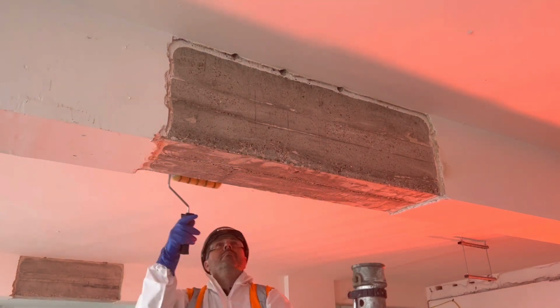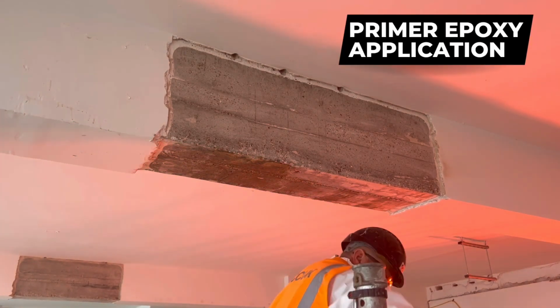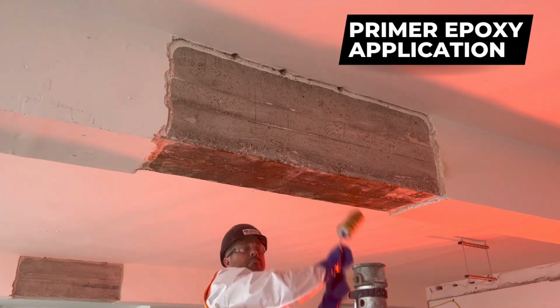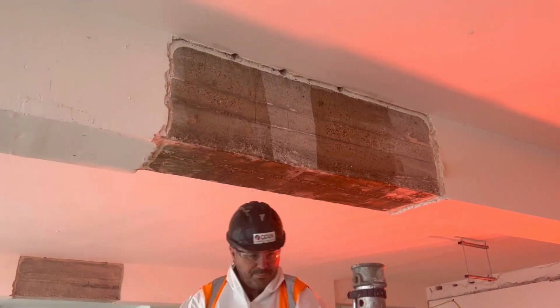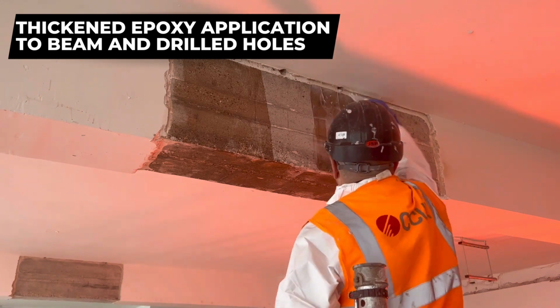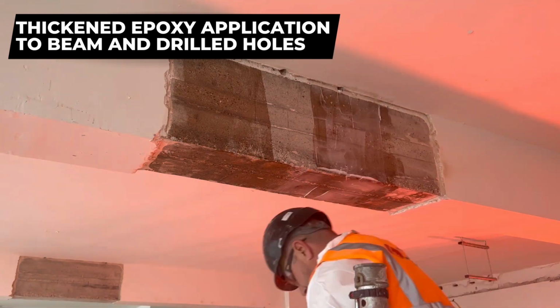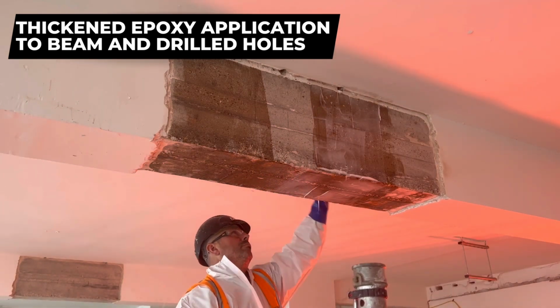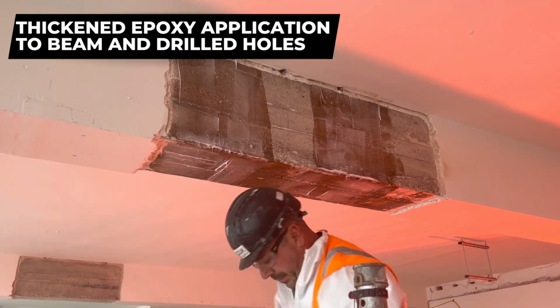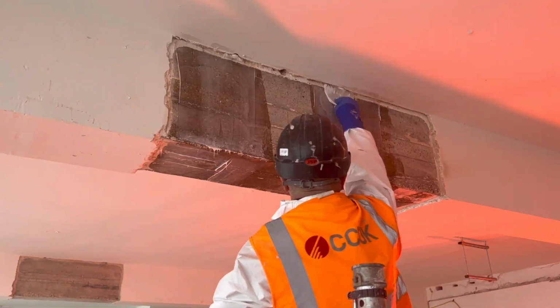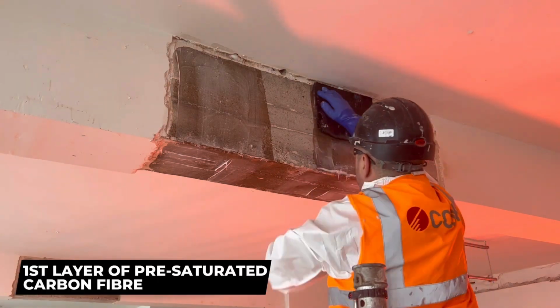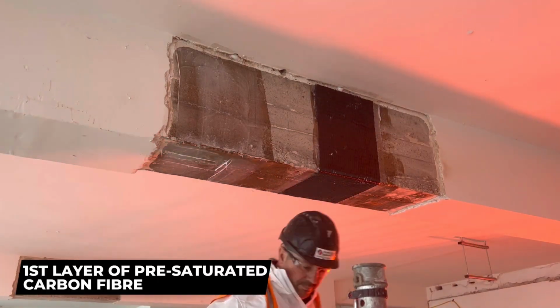Once priming is done, they apply the first coat of thickened epoxy, which you could see, the white colored stuff they are applying. And then once they have applied that coat, they'll unroll the first layer of carbon fiber there. Now the carbon fiber this guy is applying is actually saturated in a different area on the same site. So when he's applying it in this place, it is in wet condition. That's why this application is called the wet layup method.